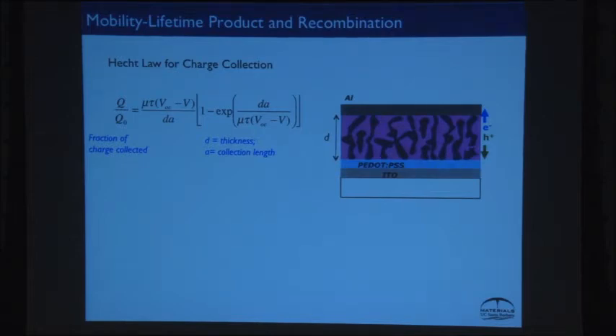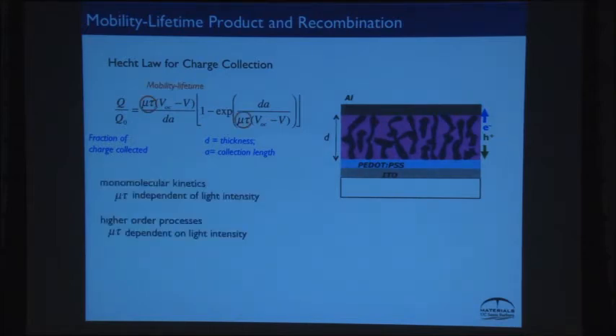So we did something very simple just to start with, where if we look at a solar cell, the fill factor is mostly about charge carrier collection efficiency. So you can use something called the Hecht law, which tells you about the fraction. If you just assume that the fraction of charge collected is related to the mobility lifetime product here, meaning how fast they move versus how long they last.